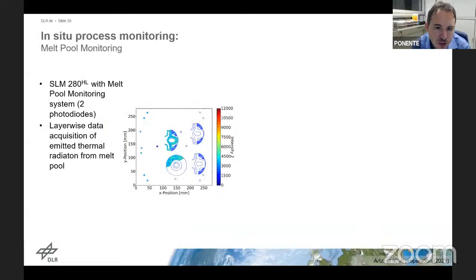For this, we can use this tool in our machine called the melt pool monitoring that probably many of you already know, because today it's more or less standard in LPBF machines. We were one of the first customers to use it. It's basically a pyrometric tool with 2 photodiodes. It records in 2 wavelength regions thermal emissions from the melt pool itself. It follows the optic of the laser, so that we get basically a thermal response from the melting material itself. Meaning it's at first order a tool for measuring the temperature or thermal emissions and the melt pool size, its convolution there. It gives you data in a layer by layer fashion.